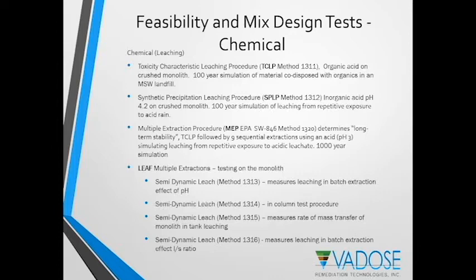Another test for evaluating chemical durability or leaching is the multiple extraction procedure, or MEP, method 1320. This is a long-term stability test. It involves essentially that TCLP test followed by an additional 9 sequential extractions, with the intention there being to simulate leaching from repetitive exposure to this acidic leachate over a 1,000-year period. So certainly a very good demonstration of long-term durability.